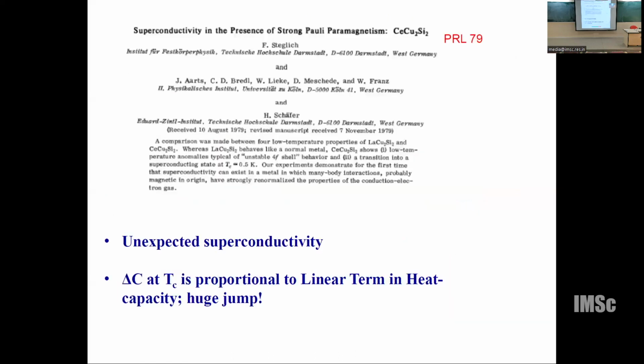Okay, now another interesting aspect. When people were studying that, in 1979, Steglich published a paper on a new compound, cerium copper two silicon two. He found the same heavy electrons, which are supposed to be essentially immobile. See, if I find superconductivity in this compound, it is exactly the opposite thing, which is not supposed to move, I'm putting it very, very loosely. Okay, it becomes a superconductor at 0.5 Kelvin.